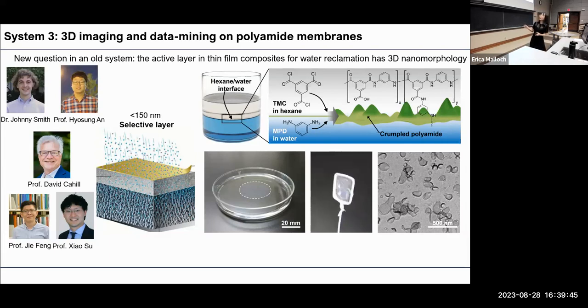Showing this schematic here, a polyamide filtration membrane is synthesized through interfacial polymerization, which really means you have two monomers, each dissolved in one liquid. And those liquid phases are not miscible with each other. So as a result, you will only have polymers reacted at the interface. If you look at the polymer film macroscopically, it just looks like one shining flat film. But if you zoom in under the TEM, you start seeing a lot of nanoscale features. Those are the features we'll later refer to as crumples.